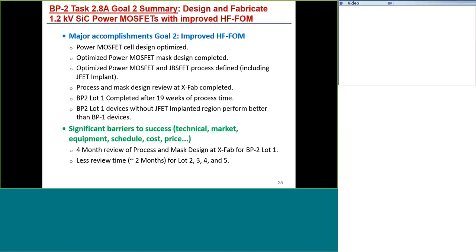So this says that we accomplished our goal in terms of making the high-frequency figure of merit devices in 19 weeks. Unfortunately, only the wafers without the JFET implant worked, and of course, the JFET implant was the innovation in our process. So we did some investigation, and we found that there was an error in processing these wafers, and aluminum was implanted instead of nitrogen. As a consequence, the devices did not work. So those wafers are now being rerun, and we hope to have results in the future.